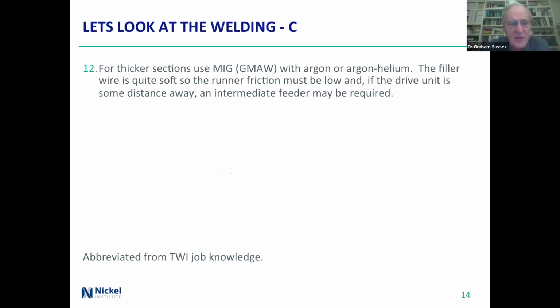And for thicker sections, you might use MIG with argon or argon-helium. The filler wire is quite soft, so your liner friction's got to be low. And if the drive unit's a bit away, then you may need an intermediate feeder, but that's all adding places where you could pick up rubbish, so you want to be careful that you're not getting contamination.